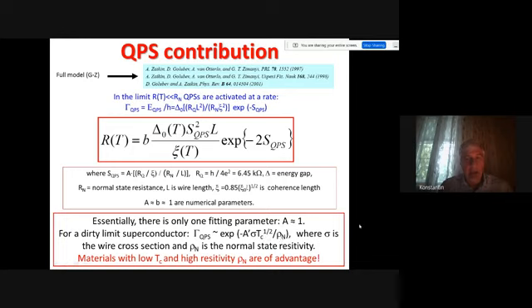So if one wants to study this effect, one should fabricate structures with as small as possible cross-section sigma, of low Tc superconductors, no high Tc at all, and which are additionally bad conductors in the normal state. So that is why mainly I will speak about low Tc superconductors in my presentation.